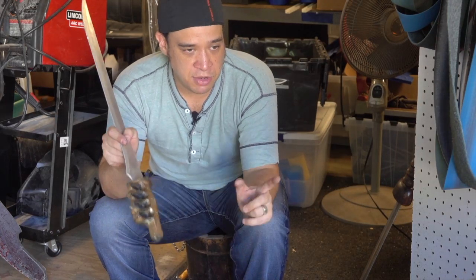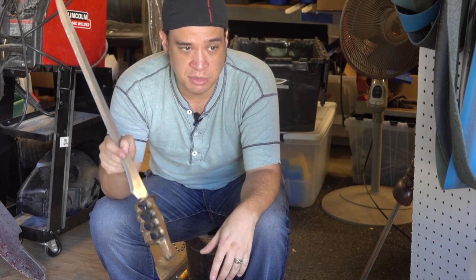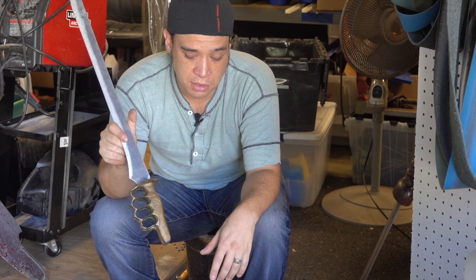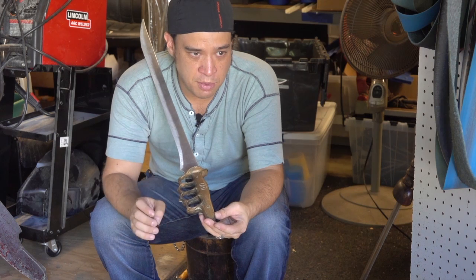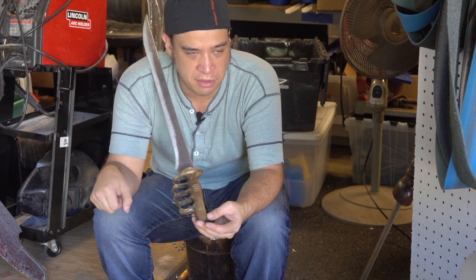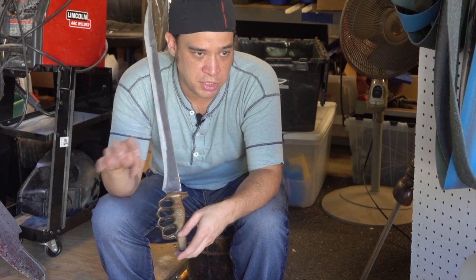Yeah, because you got to think about it. If you have one mold pouring or demolding every 6 hours, it takes a lot of time to cure. So I needed something that cured within 10-15 minutes. So Onyx is what I used on this. It's a Smooth-On product, and that way I can work with it. You have very little working time. I got a big gallon of it, and so mix, slush. You got about 30 seconds to pour it into the mold.